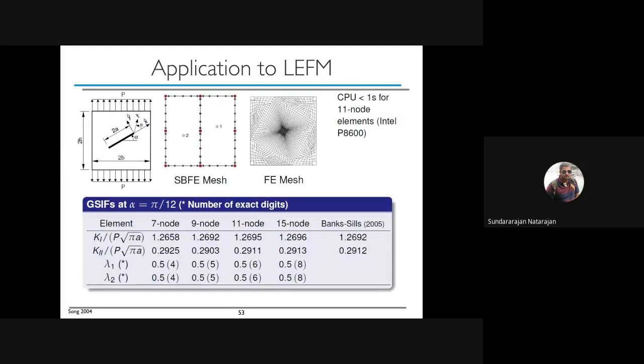So this is one classical example where you have a plate with an inclined crack of length 2a, and it's subjected to far field tension. If you look at a finite element mesh, you will see that the mesh has to be extremely fine close to the crack tip. Whereas in scale boundary, the one that you see at the middle is all that you require to solve the problem. So first of all, you can immediately see that the number of degrees of freedom is going to be extremely small. So the solution is going to be super fast. You can also use your laptop and just run the model.